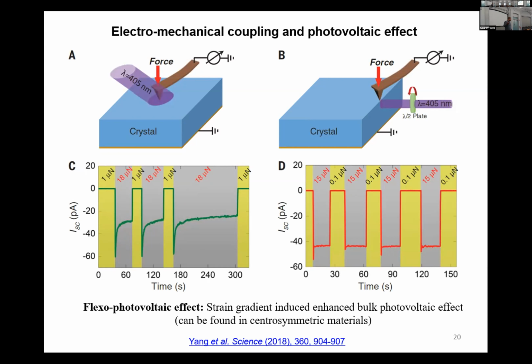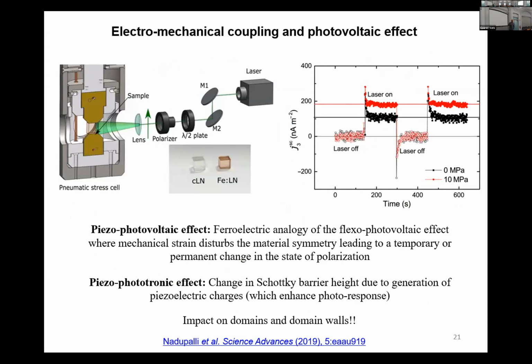And this can be found in centrosymmetric crystals. Now, learning from this, another group in Luxembourg used iron-doped lithium niobate. They applied uniaxial mechanical stress and shone the laser on the material, and they could see a difference in the photocurrent with the change in mechanical stress. They termed it the piezo photovoltaic effect. It is a ferroelectric analogy of the flexo photovoltaic effect.